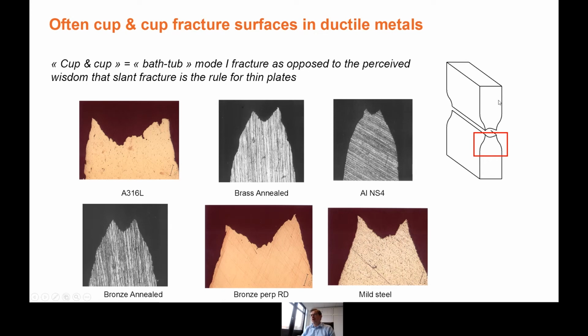It's really a bathtub shape, a cup and cup, if you want, which shows that basically the fracture strain in the middle is smaller than on the side. So the crack starts in the middle because the fracture strain is lower, and then you need more deformation to break the sides. But this is really a flat fracture in the sense that it's not a shear dominated fracture. Just the fact that the crack propagates first in the center and leaves ligament on the side, there is big crack tunneling, and it gives that kind of shape.